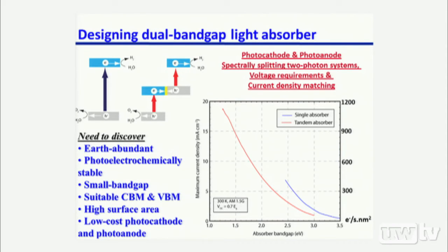Then theoretically, the maximum photocurrent density can be very high. For example, in this case, we're expecting the photocurrent output can be 20 milliamps per square centimeter. And if you can utilize all the 20 milliamps per square centimeter current for water splitting or for CO2 reduction, that means the ultimate solar to hydrogen energy conversion efficiency can be very high. So it's 20 times 1.23, it's 24%. So theoretically, the solar to chemical fuel energy conversion efficiency can indeed be pretty high as long as we can come up with the right material here.